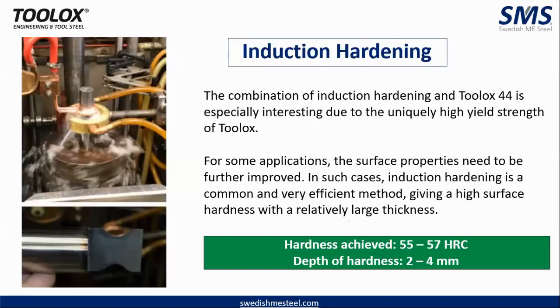So one more surface treatment process is induction hardening, which is a known process. Induction hardening in combination with Toolox 44 is particularly interesting because of the high yield strength of the Toolox. Not only the hardness that it achieves, from 55 to 57 HRC, but also the depth of the hardness that it can achieve. It can go up to 2 to 4 mm deep in induction hardening with Toolox. That can solve most of your tooling worries.